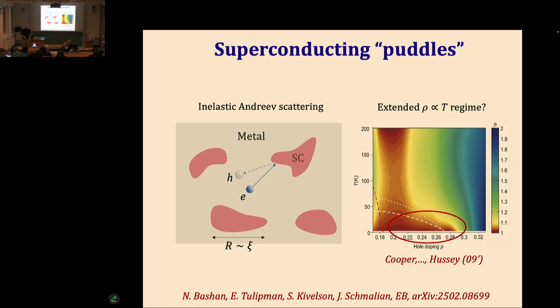What about the d-wave order parameter? The d-wave order parameter is very important to get these puddles in the first place in a good metal. Say I take an s-wave superconductor and start adding disorder. When would disorder destroy superconductivity?